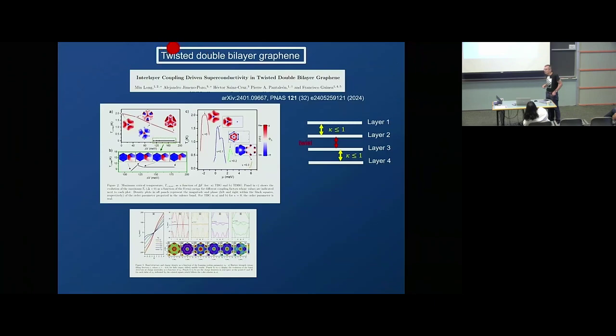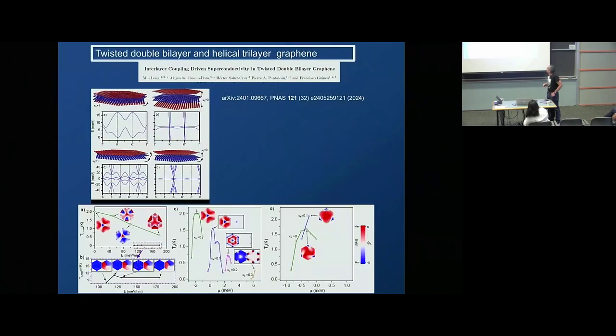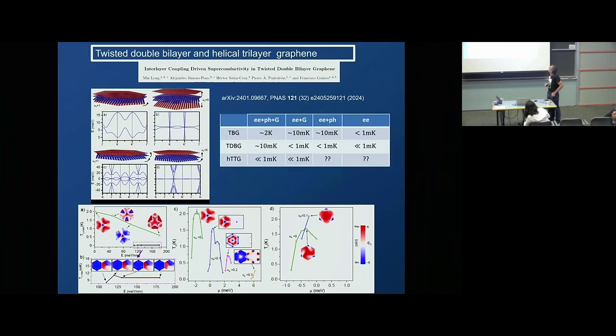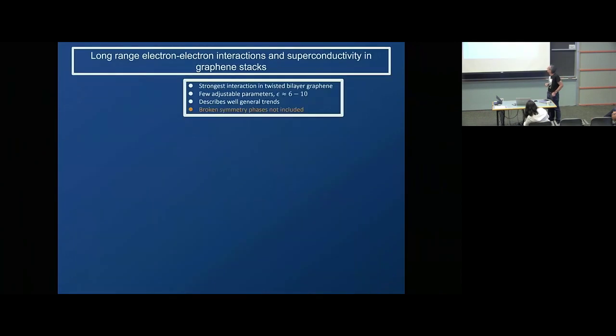So you need something with a combination of dispersive and flat bands in order to get the superconductivity you find in a twisted bilayer. We repeated the situation for a helical trilayer, and again you don't get strong superconductivity. So this is a summary: you need the phonons, you need electron-electron interaction, and you need these umklapp processes as well, both in the electron-electron coupling and in the electron-phonon coupling.